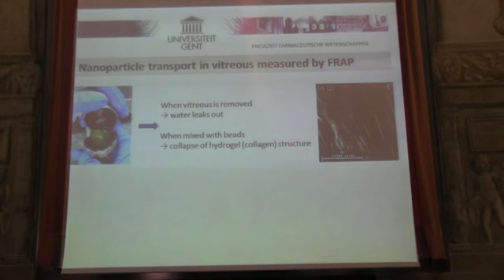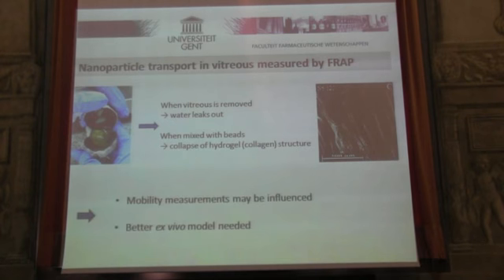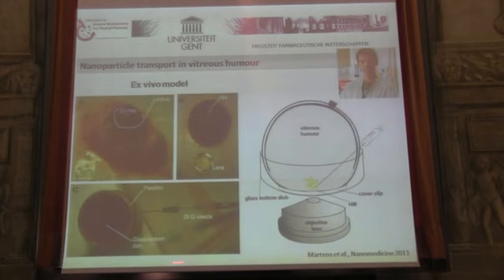However, when you look at these vitreous images on the microscope, you see that particles are mostly getting stuck in these linear structures. Those are the collagen fibrils. But we were a little bit doubtful about this model because when you take the vitreous out and you put it on the table, immediately the water starts leaking out. And then we start mixing it, so you can imagine that the structure after these manipulations is maybe not the one that's actually inside the eye. So we wanted to have a better ex vivo model, and this is what we did in recent years.